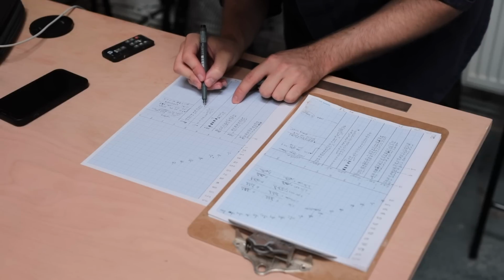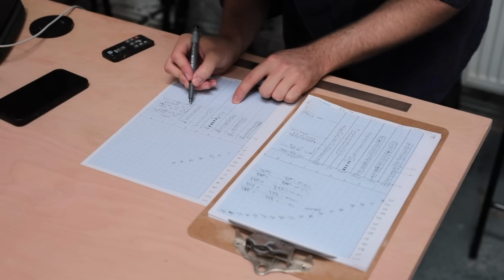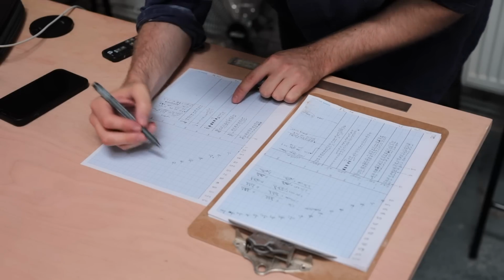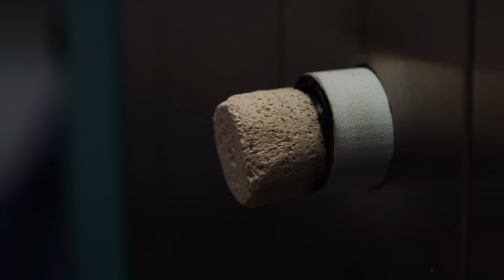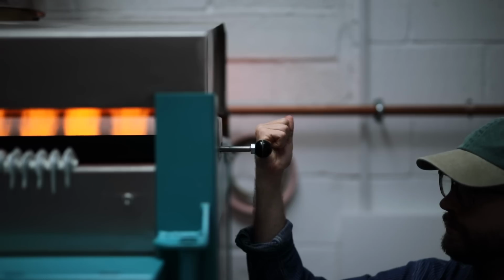I do this by increasing the gas pressure and air pressure and sliding the dampers that cover the flues to about halfway closed. This causes the fuel inside to burn inefficiently, as the gas builds up and there's simply not enough oxygen inside. As a result, oxygen is stripped away from the clay and glazes, pulling iron out to the surface as it does. And it's this process that creates the greens and blues in my glazes.